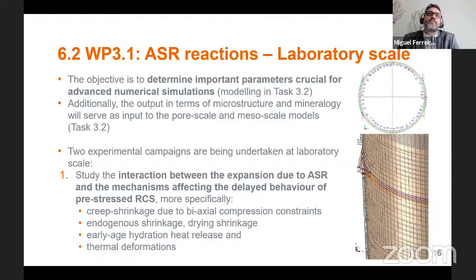two experimental campaigns have been prepared at the laboratory scale. In the first, the interaction between the expansion due to ASR and the mechanisms affecting the delayed behavior of pre-stressed reinforced concrete structures is being studied. This delayed behavior includes the creep and shrinkage due to biaxial compression constraints. So if you think about a containment structure of a nuclear power plant, many containment structures have vertical and radial or horizontal pre-stressed tendons, and this is a rather unique type of structure, and very little research has been done on how this affects the evolution of any kind of expansive reactions in concrete. Also looking at the effects of shrinkage, endogenous and drying shrinkage, and also early age hydration, heat release, and thermal deformations.